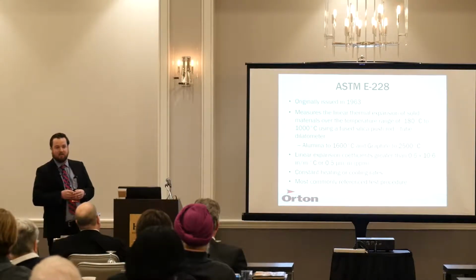Minus 180 is not a typo. We do go down to liquid nitrogen temperatures. It's always fun in lab to have the smoke bellowing out. You see stuff going everywhere, but that does provide a lot of measurements for a lot of the glass industry for the 0 to 300 measurement. That's still a low room temperature, so you have to use a cooling mechanism.